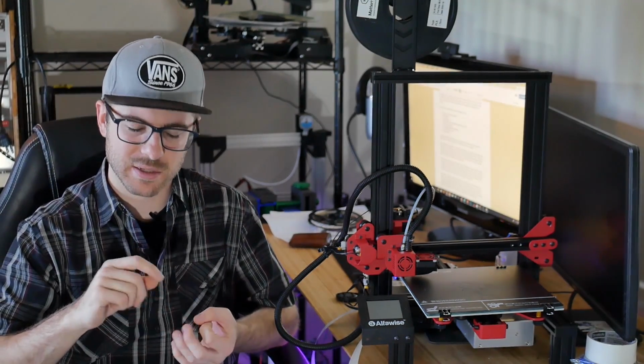Which again, I don't think in that situation was a machine thing, but more of a slicer settings issue and potentially the filament. So I went ahead and adjusted the retraction. I changed up the temperature by 5 Celsius. I lowered it actually, and I slowed down the print just a hair, and I went ahead and printed out a vase in the same material.